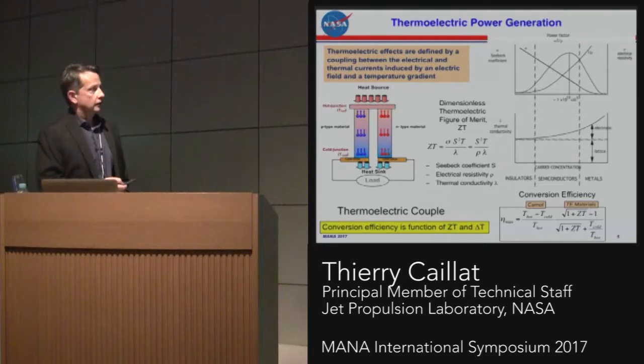Schematically, the chairperson mentioned the Seebeck coefficient. That's indeed what we use in power generation and cooling. It's a slightly different effect, but the principle is you apply a delta T across two types of elements. One is p-doped and the other is n-doped. You connect them electrically in series and thermally in parallel, you apply your delta T, you connect it to a load, and that delta T creates a voltage across this. That's the Seebeck effect, where you generate power. The thermoelectric figure of merit is a function of the Seebeck coefficient squared divided by the electrical resistivity and the thermal conductivity.